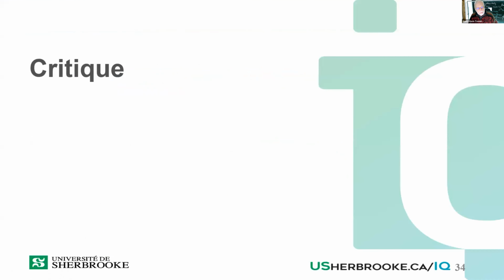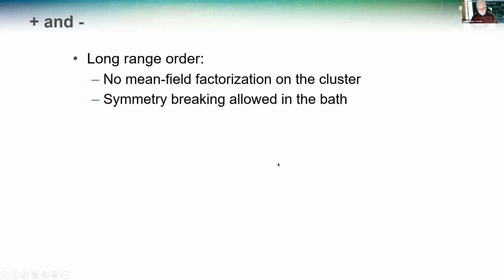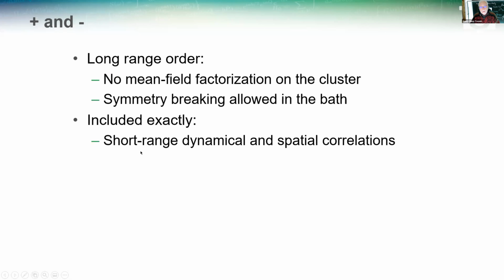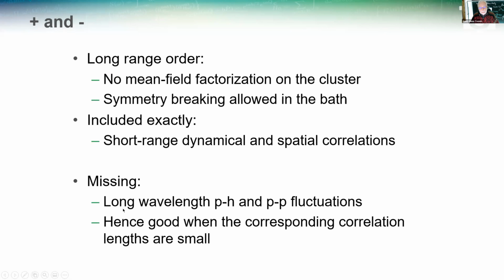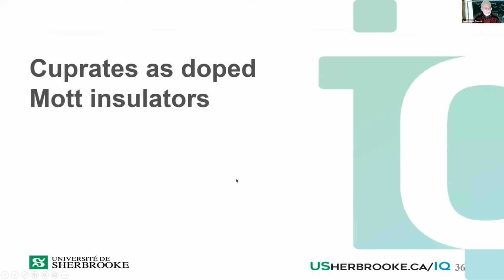Now, what are the limitations of these methods? How can we criticize them? An advantage, from my point of view, is that long-range order does not come from a mean field factorization on the cluster. Symmetry breaking is allowed only in the bath of electrons that represents the rest of the system. What's included exactly are short-range dynamical and spatial correlations. And what's missing are long wavelength particle-hole and particle-particle fluctuations. It's good when all the corresponding correlation lengths are small, so either, let's say, at zero temperature in the ordered state or at very high temperature. In the middle, it sort of interpolates between the two, but it's less controlled when the correlation length is large.